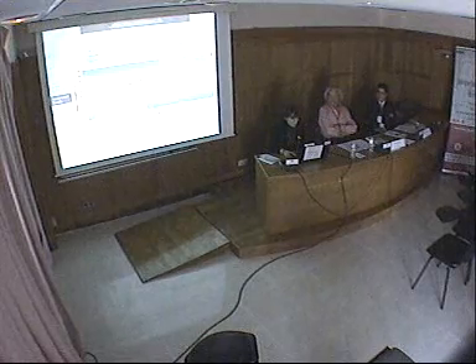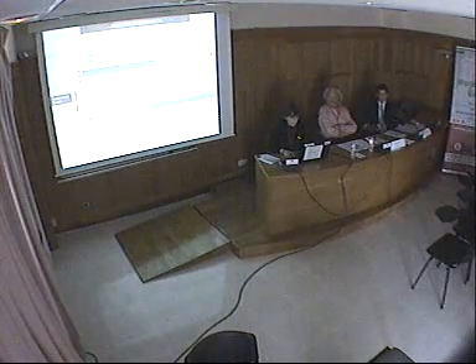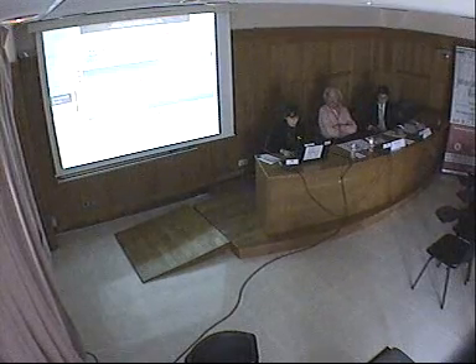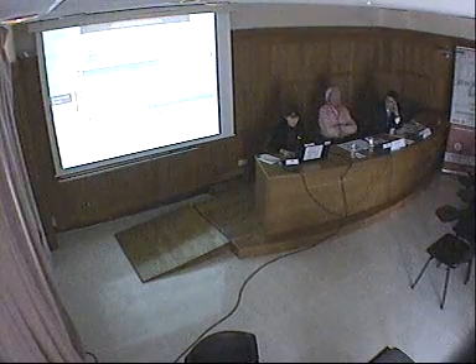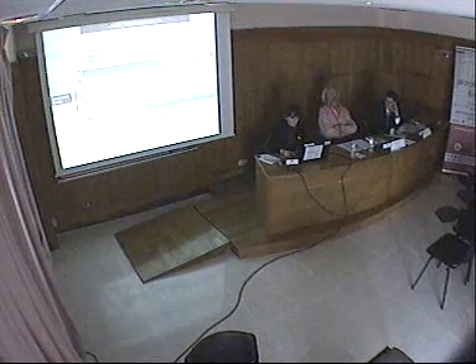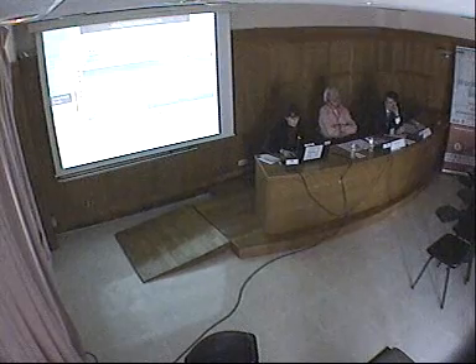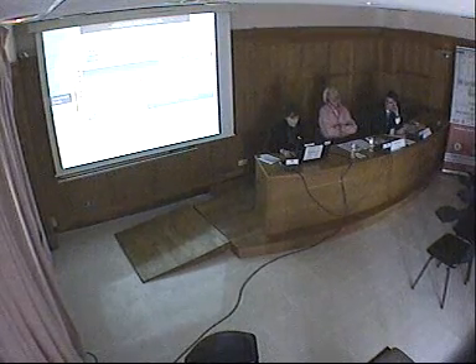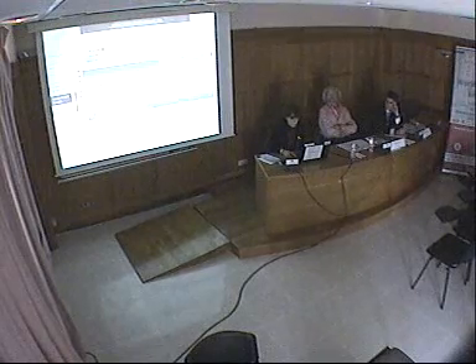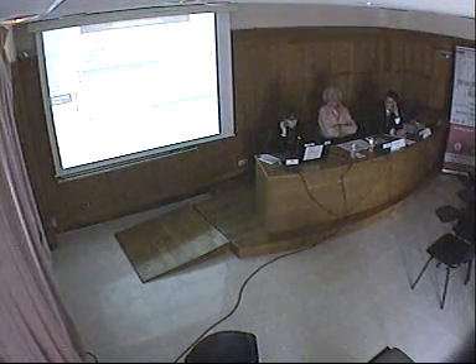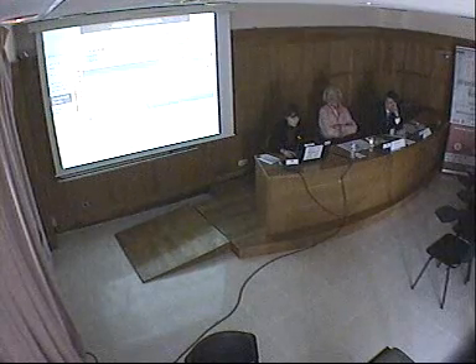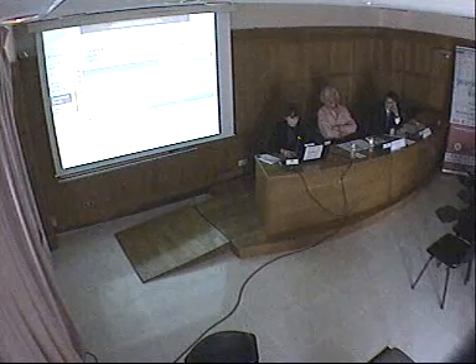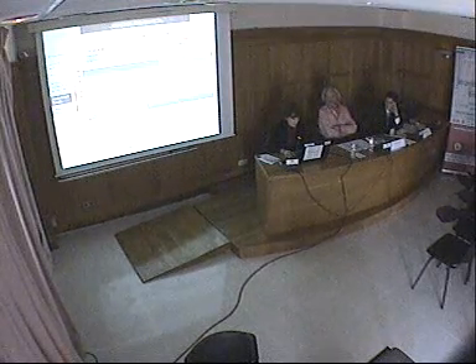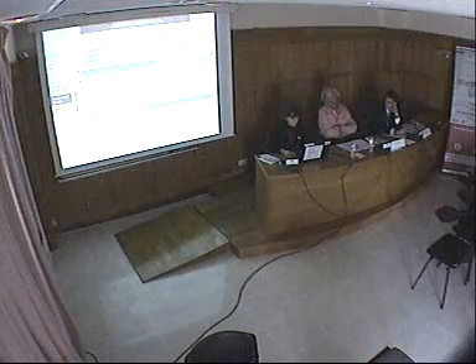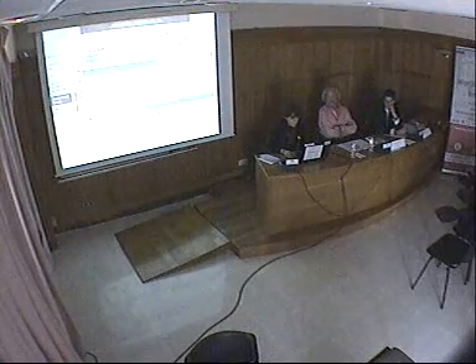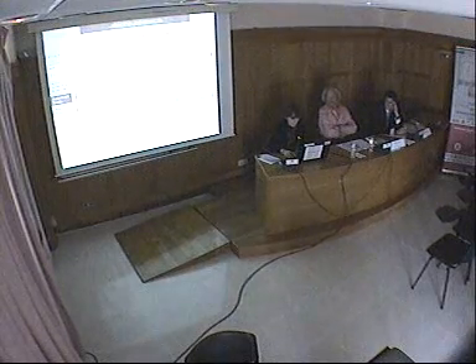By a comparison between fired clay and unbaked earth wall, in which unbaked earth is shown in red and the fired clay in yellow, you notice that by using an unbaked earth wall we can achieve a better damping of the indoor RH fluctuation. And another important remark is that the use of unbaked earth can allow us to achieve a constant relative humidity value in an average range between 50 and 70%.